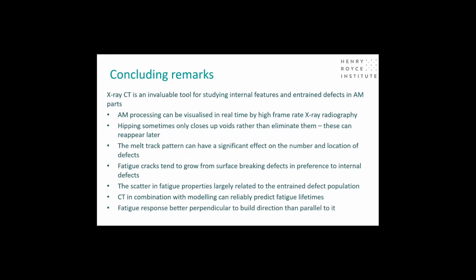Okay, and as I was saying, fatigue generally can be better perpendicular to the build direction than parallel to it. So we need to understand better how to minimize the entrainment of defects, and in particular these lack of fusion defects, which tend to be most critical to fatigue life.